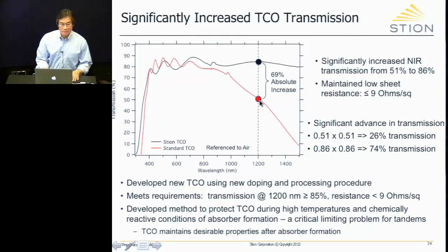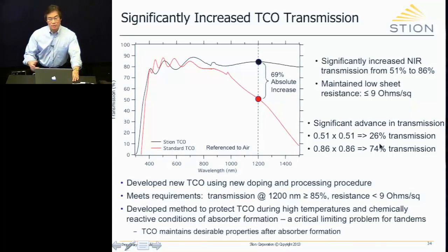I won't tell you what it is, but it's about 51% at 1200 nanometers, where the band gap is the lower of the bottom device. So at 51%, you have 2 TCOs, so 51 times 51, that's 26% transmission. Right off the bat, you've lost 74% of your light. If you do nothing else, you've just lost the game. Right? Yes?